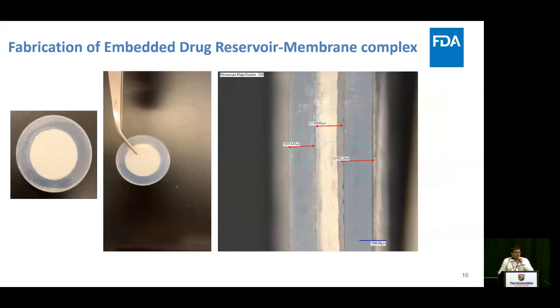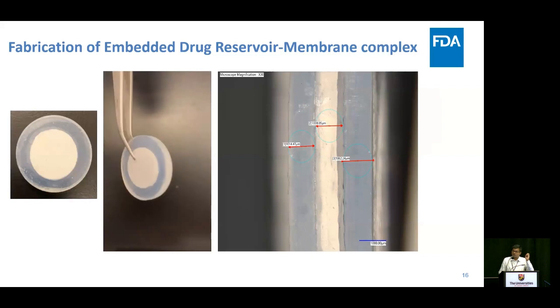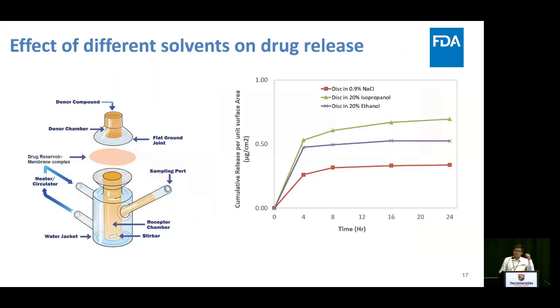As you see, the drug reservoir is totally embedded within the PDMS matrix. And the only difference from the device itself is the thickness of the membrane. Here it is around 1 millimeter, while in the device itself, the thickness of the PDMS membrane is 0.3 millimeter. We use this to do short-term accelerated release studies in the solvents that were predicted by the HSP and also by partition coefficient determination experiments. That data I'm not showing here due to time constraints.